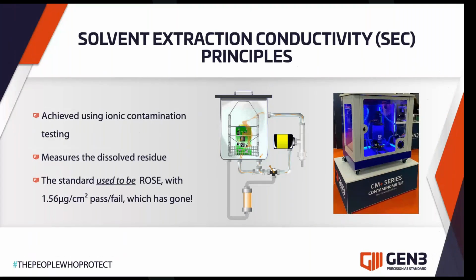Thank you, Andy. So solvent extraction conductivity testing, we have an alcohol water solution into which we put our product, our surface test assembly, and we dissolve off the ions, which then pass through a conductivity cell. So we measure the residue that can be dissolved off. This approach has been around for more than 40 years, and as Andy just mentioned, it was previously known as the Rose technique. And it had a pass-fail level that came about from the technology at the time the test was brought into existence.